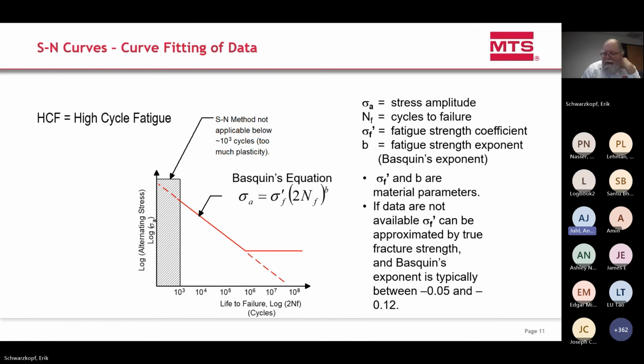The SN curve can also be fit by an idealized solution. It's primarily a straight line on a log-log curve, so there's an exponent, a fatigue strength exponent, in Basquin's equation. There's also a fatigue strength coefficient, which indicates where that line intersects zero, or one, on a log-log curve. Once you record these coefficients, you can generally use them in any kind of design at any stress amplitude you need, and predict the number of cycles to failure.